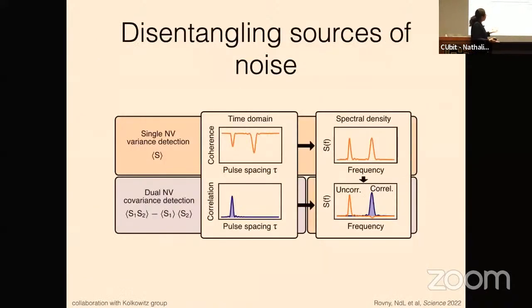Okay, so what can we do with it? One of the things that we can do is disentangle different sources of noise. Let's say we had 2 sources of noise where one was correlated and one was uncorrelated. If we were looking at a single NV center, we would basically just do some coherence measurement. We'd see a couple of dips and then transform that into a spectral density of the noise and see 2 peaks. And then if we do this covariance detection, what we should see is that only the correlated noise shows up in covariance. And then now we can label these 2 peaks as being either correlated or uncorrelated noise.